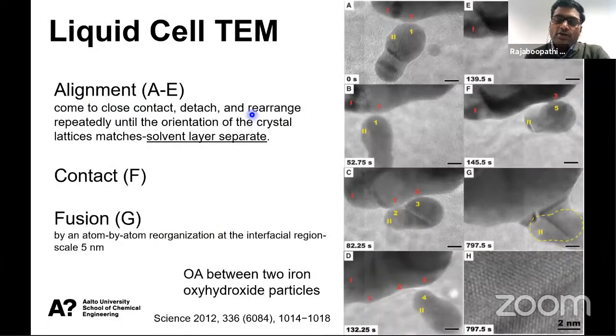So how to see what is happening inside the solution, whether it is oriented attachment or mesocrystals, how to confirm it? We can use liquid cell TEM. TEM is normally used for solid samples. We can also use a liquid sample holder to see what is happening at the liquid level or in the supersaturated solution. This is a liquid cell image of oriented attachment. Here, this is one particle, this is another particle. It is not just happening, just attaching two particles.